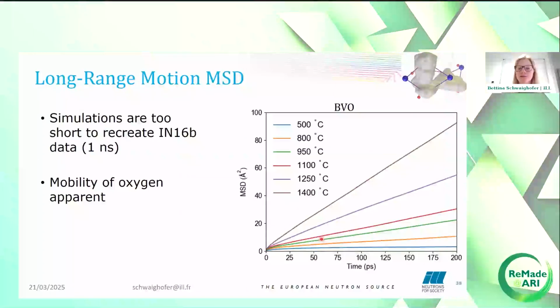Our simulations are unfortunately not long enough to directly compare them to IN16B measurements, since this would require us to simulate nanoseconds of data. However, we can still get an idea of the oxide ion mobility from the simulations by looking at the mean square displacements. Generally, the mean square displacement, here shown for BVO, increases with increasing temperature.